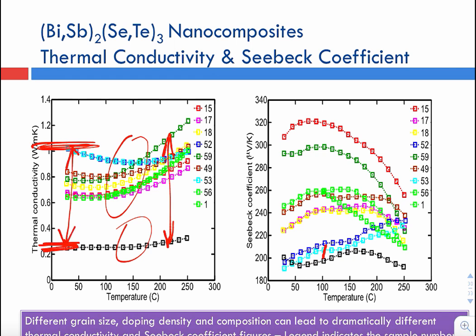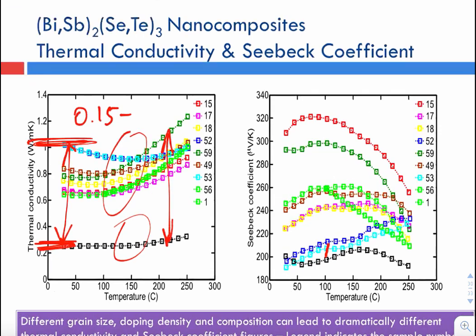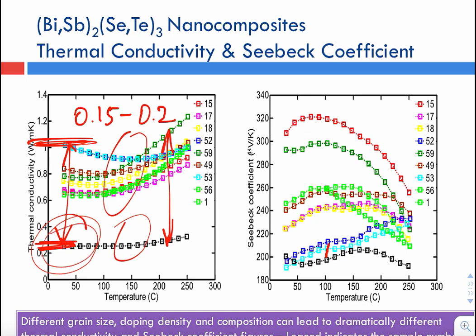Just to give you an idea, plastics like polyamide or PDMS have thermal conductivity values on the order of 0.15 to 0.2 watts per meter Kelvin. When you have a semiconductor material with a thermal conductivity of 0.2, your semiconductor is behaving almost like a plastic — essentially a thermal insulator, which is great. But at the same time, the Seebeck coefficient is also changing. You can see that the lowest thermal conductivity also gives you the lowest Seebeck coefficient, which is bad. So it's an optimization problem — for a particular application, your Seebeck coefficient may not be as important as the thermal conductivity.